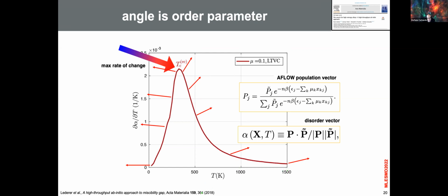So you can calculate the angle with respect to the two. You fix a reference. I don't remember where I fixed a reference, but I think I fixed it at infinite temperature, which was easier. And then you calculate the angle of your vector with respect to the reference. Then you lower the temperature, or you change the chemical potential if you want to go to the grand canonical. The positions in which you have the highest change of this vector, because this vector really moves slowly. Look at my hand, right? It moves slowly, pa, moves suddenly, right? Pa. The position in which you have this big jump, which you can get from the gradient of the angle with respect to temperature, is the miscibility gap. That's our definition of miscibility gap.